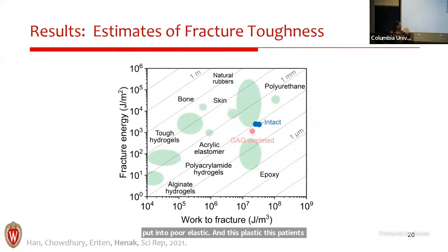So we use those data points that were on the left of the last plot then to estimate our fracture energy and work to fracture. And what you see here are the 3 dots from our experimental data. For the intact, which is the blue, we have 2 dots because we had 2 loading rates where we were in that pre-relaxed regime. And for the GAG depleted, we have just that 1 dot. And then this plot also gives you some comparison to other common materials. So we've got a pretty tough material in cartilage, which has been described before.